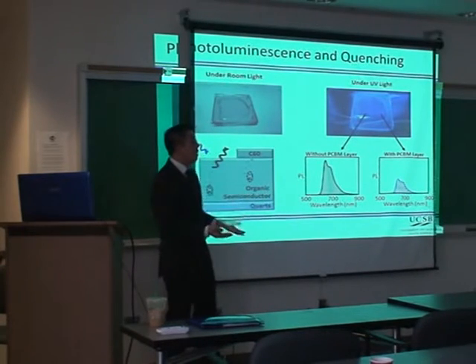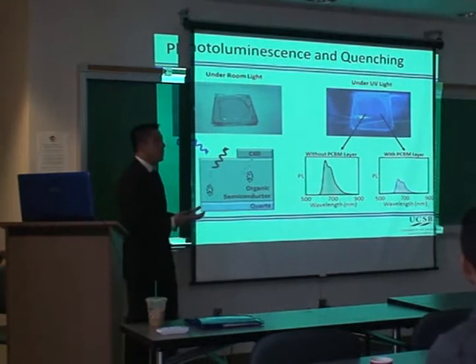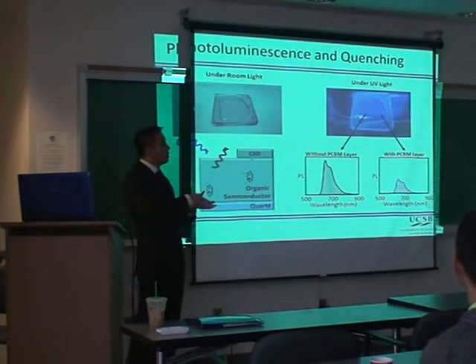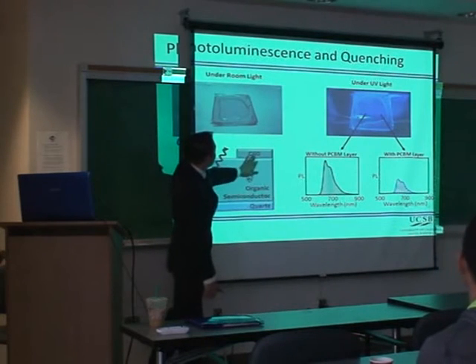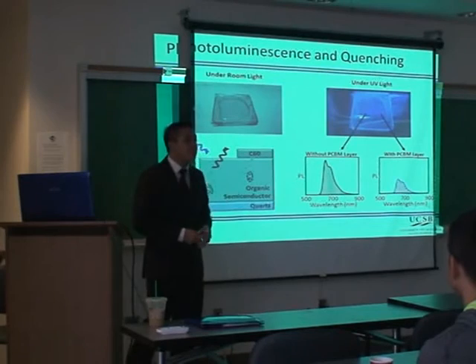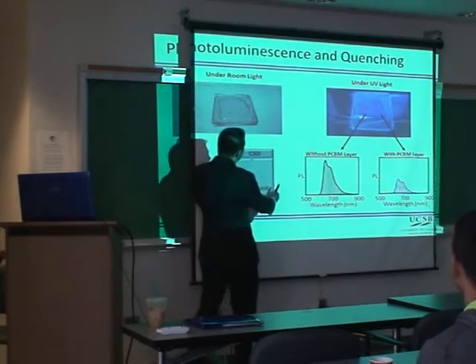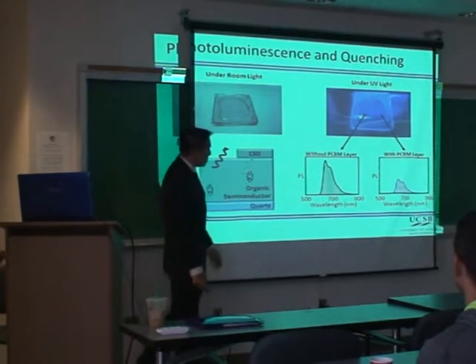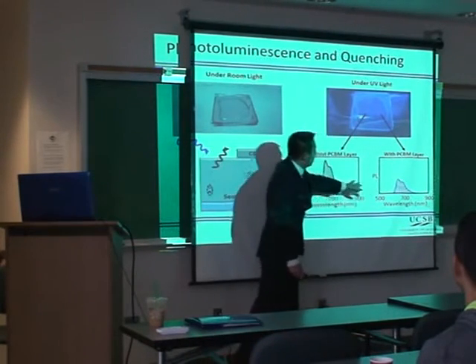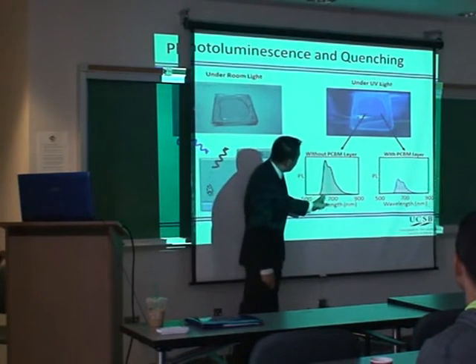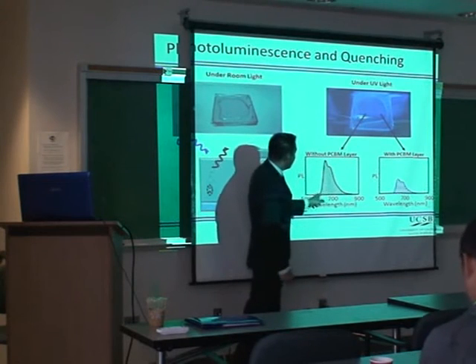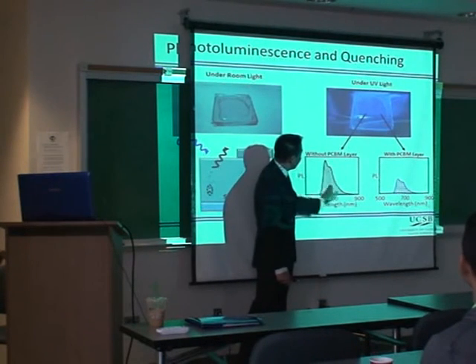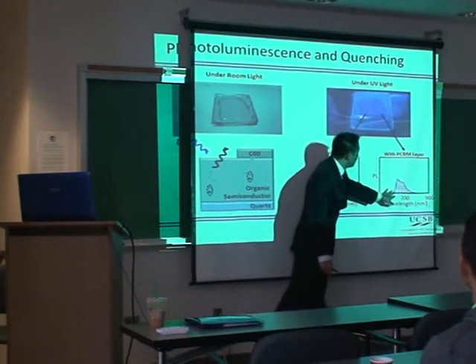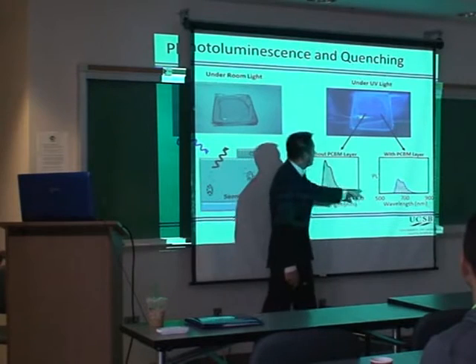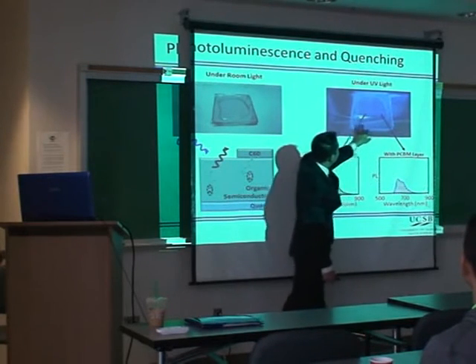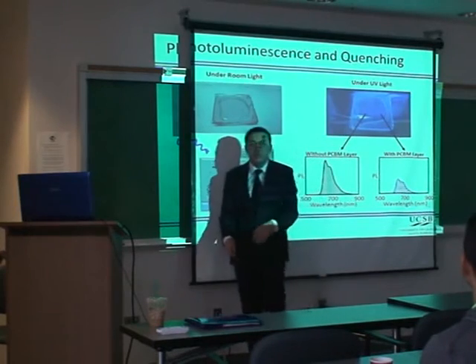And therefore, they would not be able to relax. Because one of the processes that excitons can do is that when they relax down to the ground state, they can emit light. So these excitons that are quenched at the C60 have no chance of emitting any light. Therefore, the amount of light emitted by the right side will be less compared to the left side. And we can actually see that in the spectrum. So when the exciton relaxes back down, it emits a couple of different wavelengths based on the energy levels in the material. So you can see we have most of them emitting around 700 nanometers. And if you compare the 2 sides, we can see the area underneath the curve is different. And what that means is that there's less total photoluminescence from the right side compared to the left side because the right side is being quenched at C60.